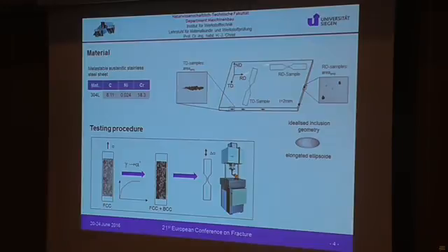This means that if we extract samples parallel to the rolling direction and we look at metallographic sections perpendicular to the applied stress, we can find sections of these inclusions with a circular shape and a small area. On the other hand, if we extract samples perpendicular to the rolling direction, so in the transversal direction, called TD samples, the projected area of such inclusions would have an elliptical form and would have a larger area. These two conditions were systematically investigated, and the results of the fatigue tests will be presented in this presentation. So the only difference between the RD samples and the TD samples is the orientation of the internal inclusion with respect to the applied load.